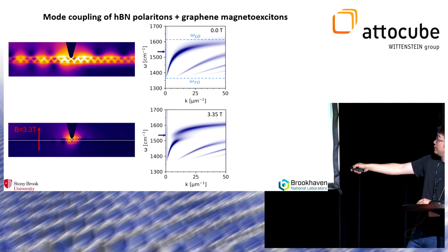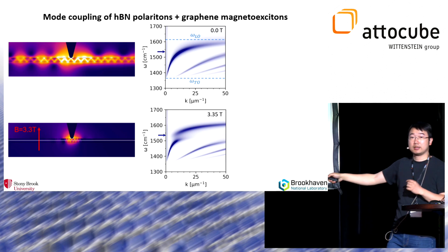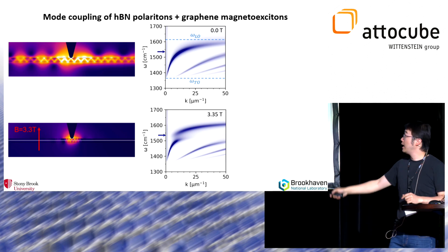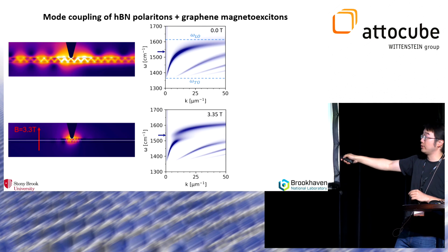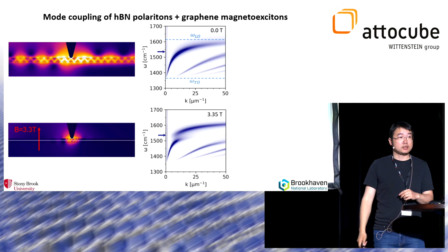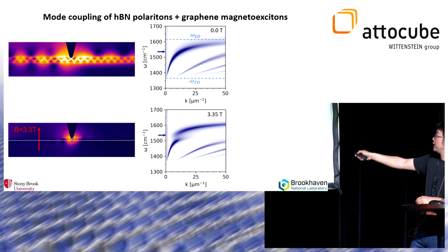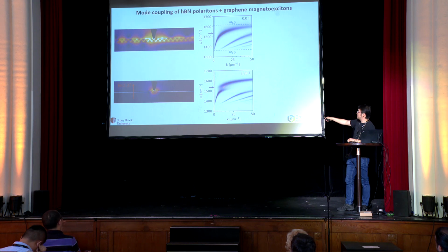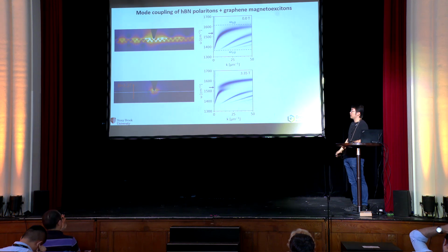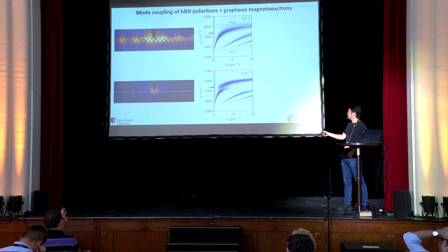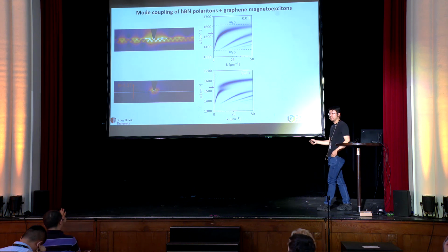And in high magnetic field, at 3.3 Tesla, your -2 to 1 transition happens to interfere with this phonon polariton mode. So we can apply magnetic field so that this -2 to 1 transition intersects here. And this is actually a strong coupling because you see a mode gap here.